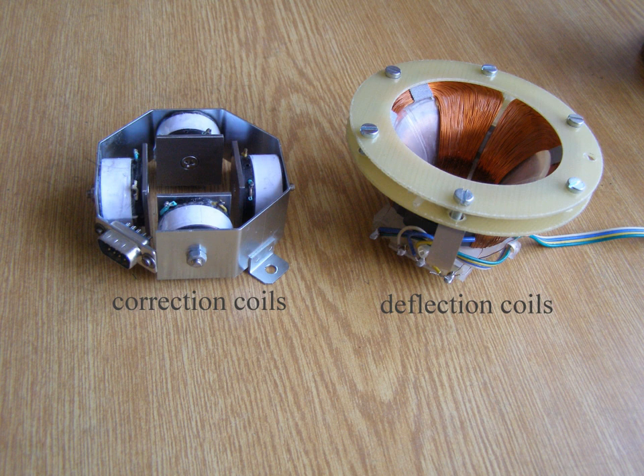Because electrons transfer their energy into heat in a very thin layer of the solid, as explained above, the power density in this volume can be extremely high. The volume density of power in the small volume in which the kinetic energy of the electrons is transformed into heat can reach values of the order 10^5 to 10^7 W per cubic millimeter. Consequently, the temperature in this volume increases extremely rapidly, by 10^8 to 10^9 K/s.